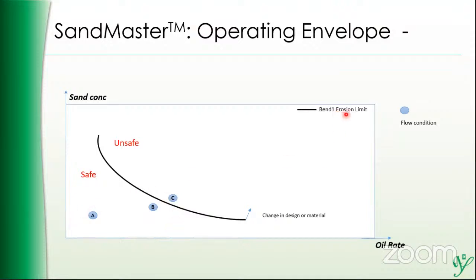That means the software will ask you what is your limit of erosion that you can allow. So if, let's say for example, you enter that I can allow up to 0.1 millimeter of erosion per year. If your current erosion rate calculated by the software is less than 0.1 millimeter per year, your operating point will lie below this curve, which will be either A or B. But if your current erosion rate is greater than the cutoff limit that you have defined, the operating point will be somewhere above this curve, which means that you are in the unsafe zone. So first of all, the first analysis you can do or you can show is that, okay, right now with a certain metallurgy, certain metal properties and component properties, you are in the safe zone.